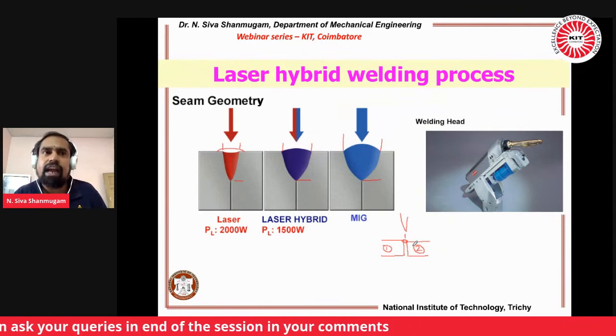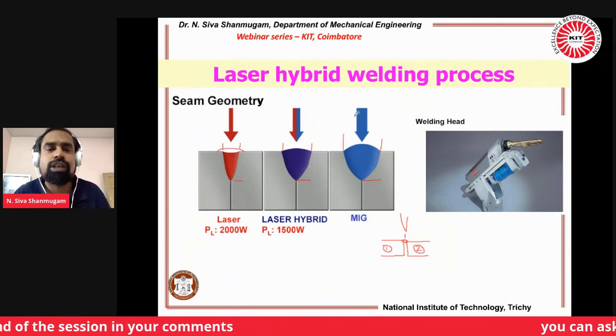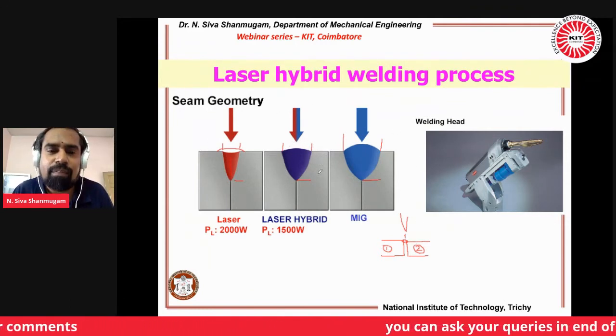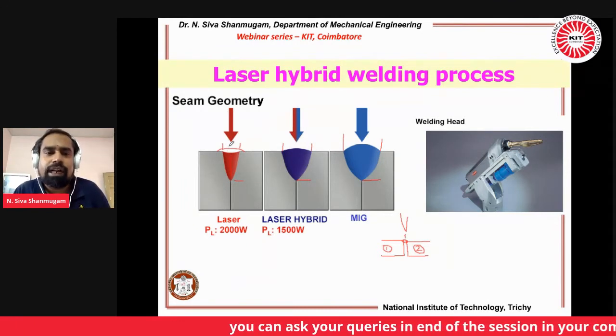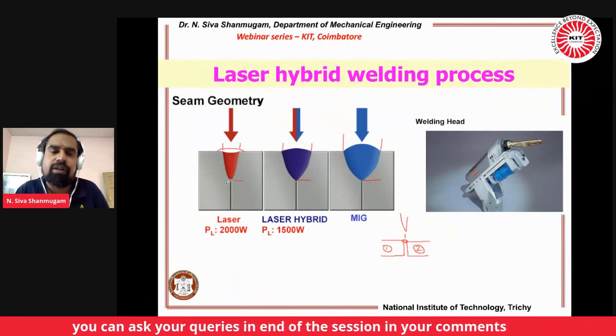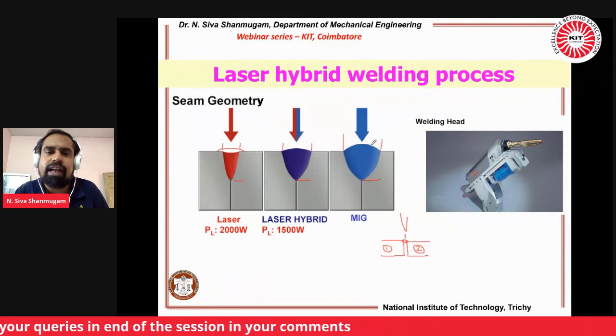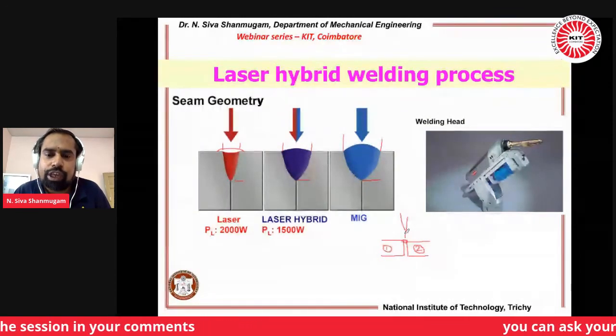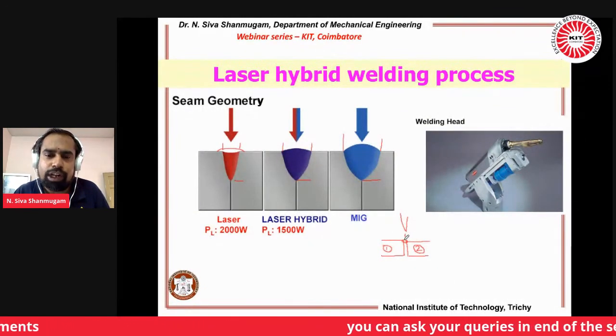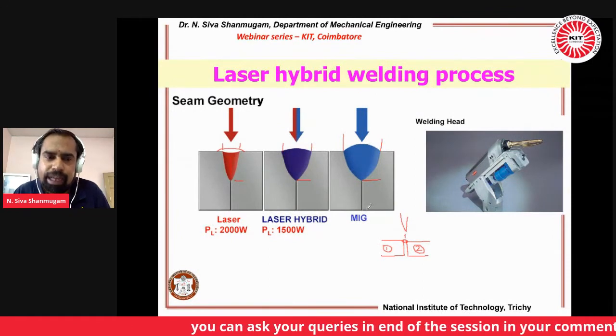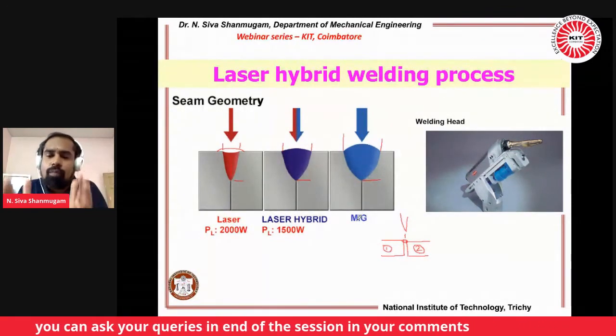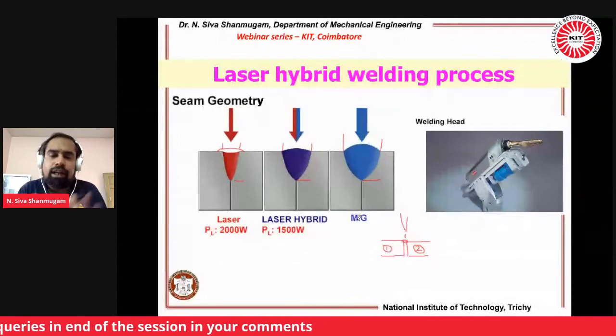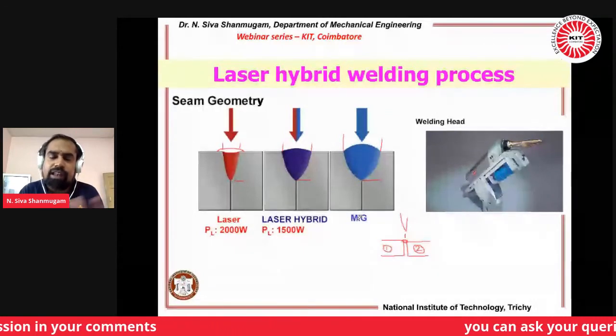If I maintain a gap of around 1 mm, you use this laser hybrid technique, because you get the advantages of deep penetration from the laser and very high bead width from the MIG. So even though you are maintaining a 1 mm gap, you are using a MIG as a hybrid, because both are joined together. Laser plus MIG torch are combined together.